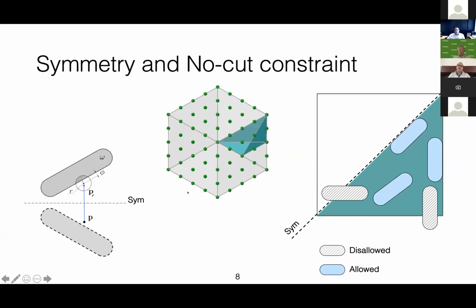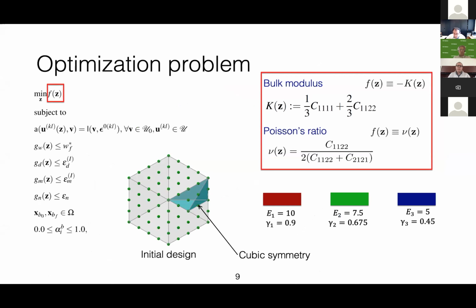And we can do that for an arbitrary number of symmetry planes. And then we just compute the projected density. And so essentially, we only have bars defining this reference region. And the no-cut constraint ensures that no strut is cut either by the symmetry planes or by the boundaries of the unit cell, because otherwise we end up with these partially cut struts that give us designs that are a little more difficult to manufacture.